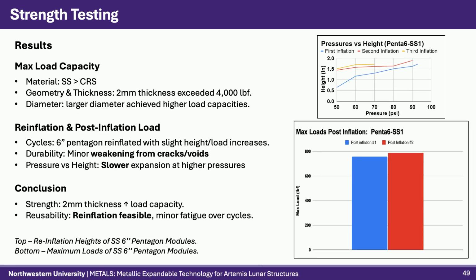From a 6-inch, 1 millimeter stainless steel pentagon, it was revealed that repeated compression inflation cycles could be achieved, as seen from the graphs, with slightly higher load capacities and inflation highs each time. However, this could result from material weakening due to crack propagation or void expansion. Nonetheless, this still highlights the great strength that lies within metal inflatables and their potential for repeated use.